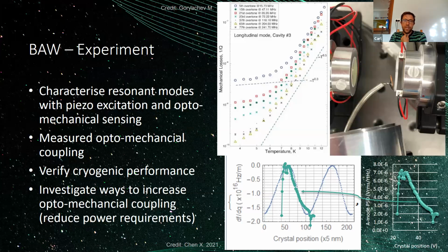So this is work by Sunday, and the top left figure is the measurements by Maxim and Mike Tobar's group showing these incredible Q factors. You see mechanical loss approaching 10 to the minus 10 at a few Kelvin. And some hot off the press results from Sunday in the lower figures show how the optomechanical coupling is about what we expect. Top right is a figure showing what's being done at present, which is just piezo excitation of the bulk acoustic wave resonator, the little lens here that sits on a piezo, and we're just measuring the optomechanical sensing side of it.